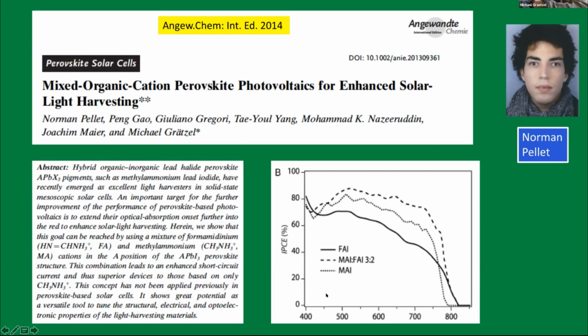And you can also see here already the formamidinium itself, the dashed line, shows a much steeper response, goes further into the red. So as a single cell, you want to be as close as possible to the Shockley-Queisser limit in the light absorption. That would be around 900 nanometer. So shifting towards this limit gives you a higher efficiency, at least the theoretical efficiency goes up.